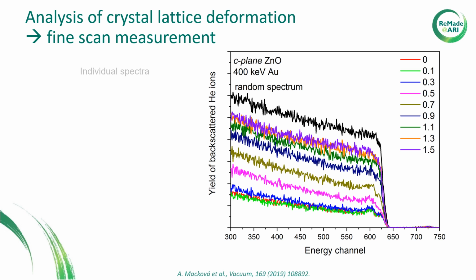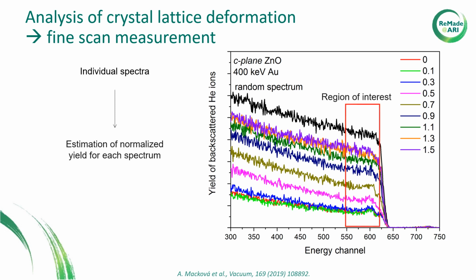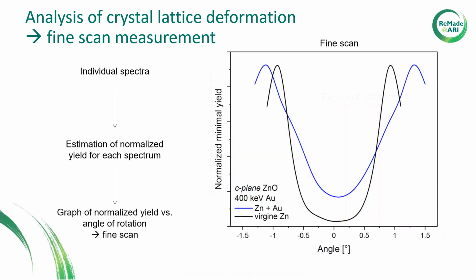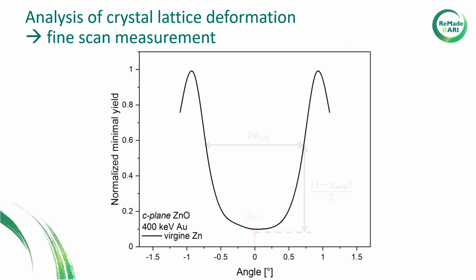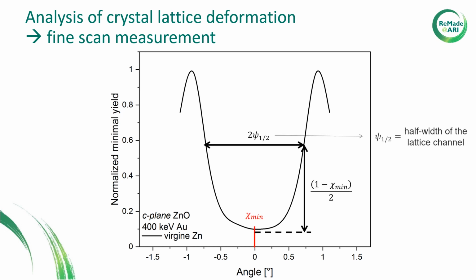During the fine scan measurement, we record multiple spectra and we estimate the minimum normalized yield for each of them in the investigated region. In the next step, we plot the dependence of the minimum normalized yield on the angle of rotation calculated from the center of the channel. The channel width is then evaluated as the half width of this plot estimated at half of the channel depth.